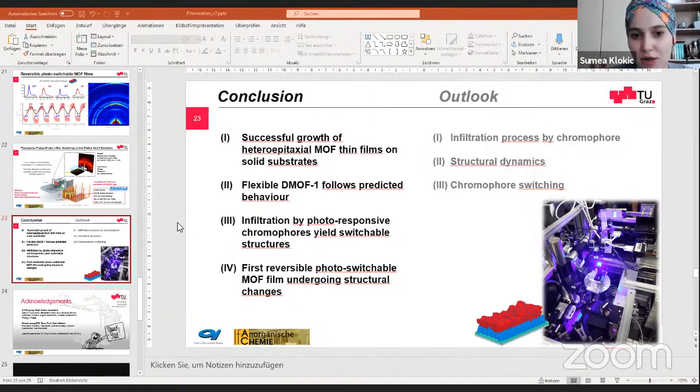Well, the structures are metal organic frameworks, and they themselves are pretty stable. What we have seen so far is that when we apply very high repetition rates with the laser, we see some kind of, let's say, ablation of the structures and so on. But what we did not see is that the azobenzene itself is destroyed, or that it goes out of the pores. The concept with the MOF and the infiltrated azobenzene inside was shown and proved already in the work of other people to be quite stable, let's say.